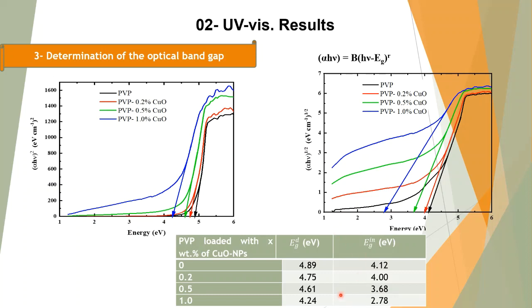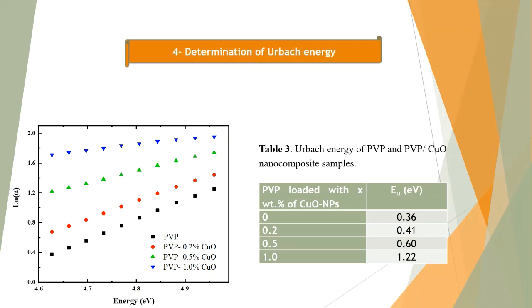The decrease in the values of the optical band gap energies may be a result of the creation of localized states within the forbidden band gap and the transitions of electrons between these two levels. We determine the value of the Urbach energy in order to determine the width of the localized states within the forbidden band gap using this equation, and also by plotting ln alpha as a function of the photon energy. As we can see from the figure, the values of the Urbach energy can be obtained by calculating the reciprocal of the slopes of the linear portion in the higher energy area of these curves.